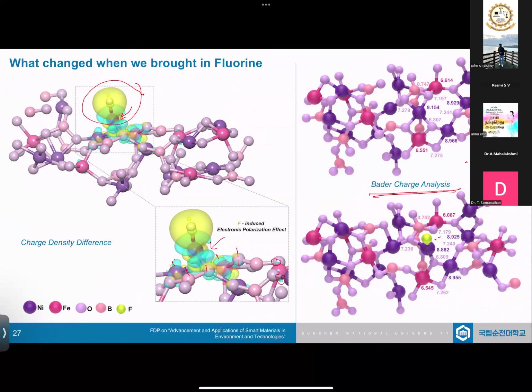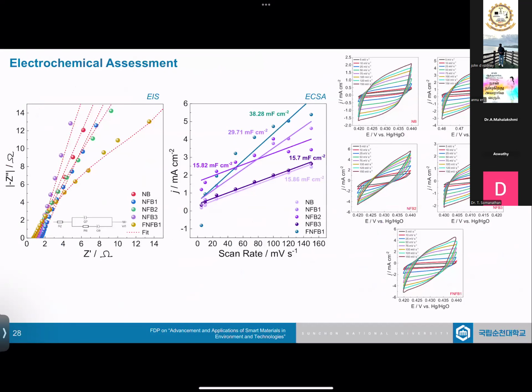And we confirmed that adding a small amount of fluorine completely alters the material's activity. This is a very important thing to understand. Now the question comes up: how does it have an impact on our electrochemical system? So I'll move much faster over here. We have the EIS, where we confirm that the solution resistance is lower and the internal resistance is much lower.